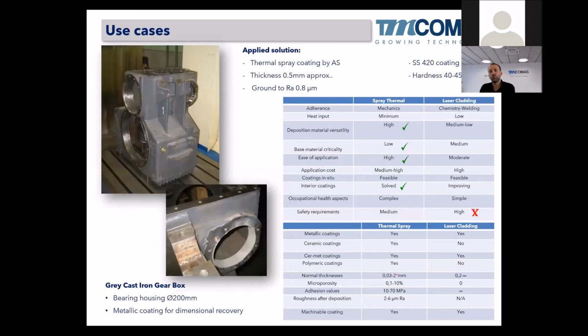And now it's time to start talking about some real use cases, where I will try to explain why we are using thermal spray or why we are using laser cladding, depending on the real case. In this case we have a grey cast iron gearbox for the railway industry, and in these bearing housings there was some wear. So the bearing was not fitting properly in that seat. So we need a dimensional restoration of this area.